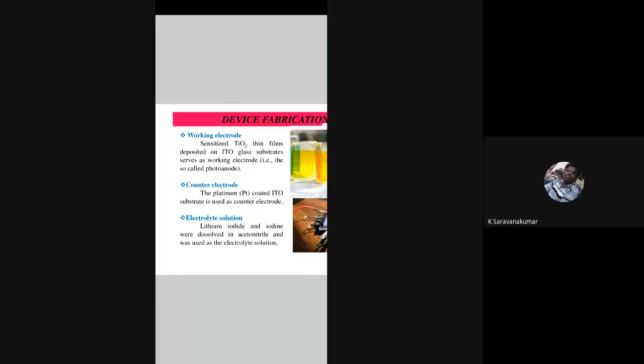And the second one, counter electrode. The counter electrode is prepared by coating platinum on ITO substrate. For this, platinum chloride is dissolved in 2-propanol solution and spin coated over ITO and annealed at 500 degrees Celsius. And the third one is the electrolyte solution. Lithium iodide in acetonitrile is used as the electrolyte solution.